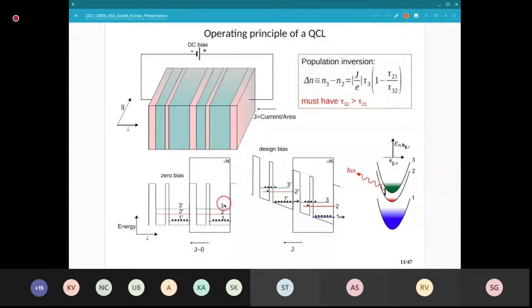And the way it works is at the ends, you apply a DC voltage, even a battery. A typical voltage that we apply is 10 volts across the 10 micron thickness. So then you establish a DC electric field across the structure, which bends the band diagram because you're applying a potential with distance. And that bending of the band diagram moves up these energies. So now you can have these energy alignments. And by resonant tunneling, when the lowest state in one of the wells aligns with a higher state in the adjacent well, electrons can tunnel through. So quantum tunneling, or resonant tunneling as we call it, is the key to how these structures operate.